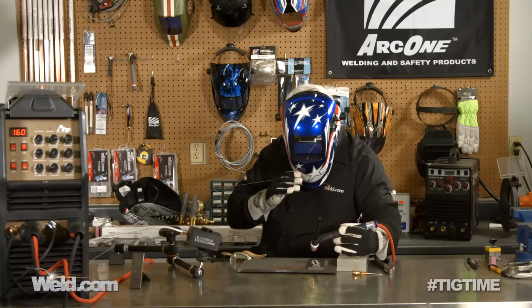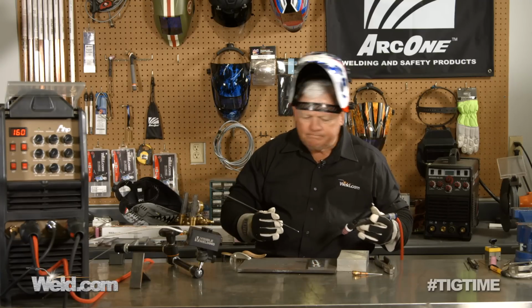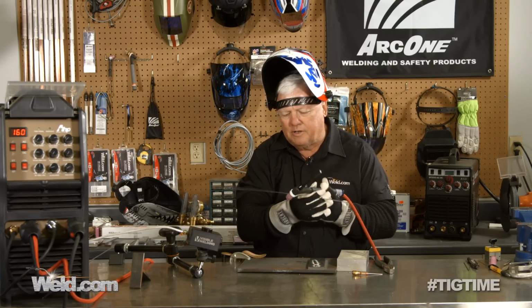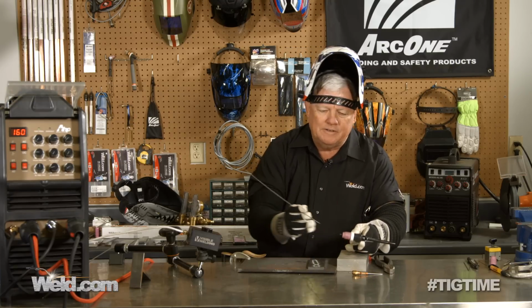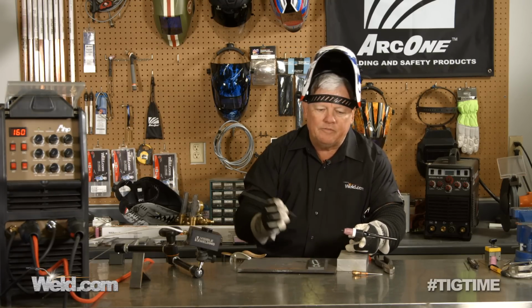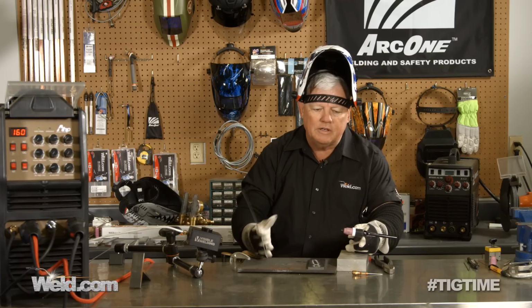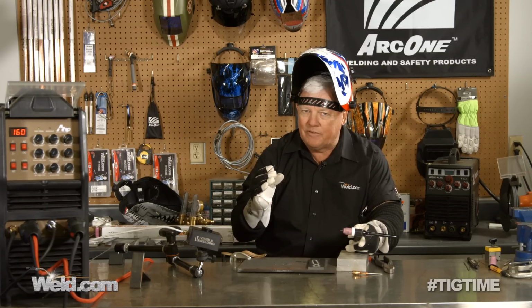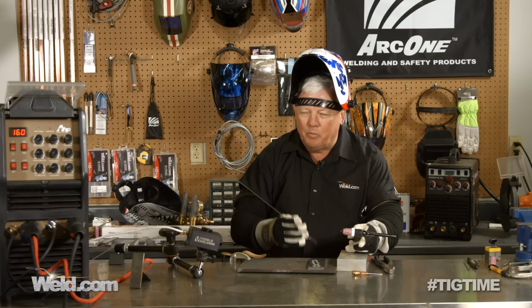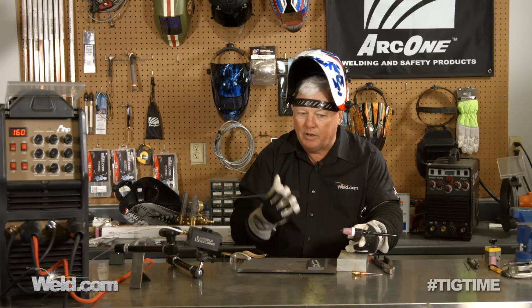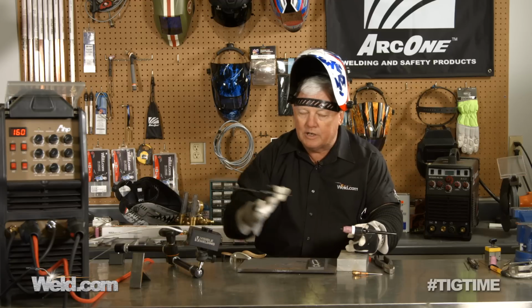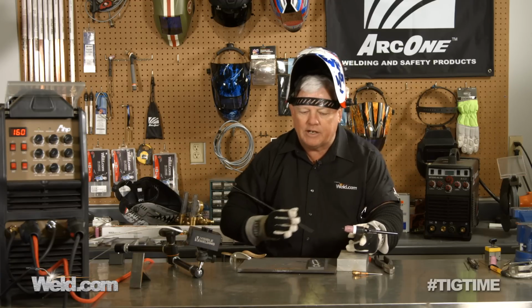Okay, I'm going to go ahead and terminate the weld. Back off very, very slowly, because it has a tendency to crater crack if you don't. So 3/32 is the right selection. If you take a look at the tungsten, it may have balled back a little bit, but not very much. It sustained the point, and it also allowed the arc to stay very, very tight. With aluminum welding, it's always really hard to get a small weld, so grinding it to a point using an inverter style machine is an advantage.